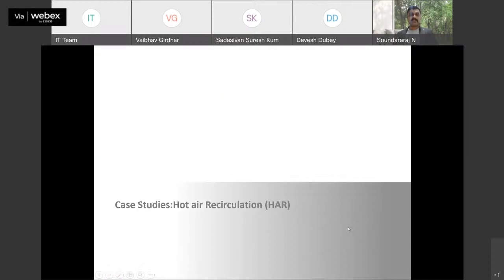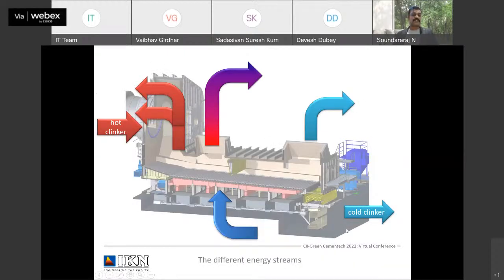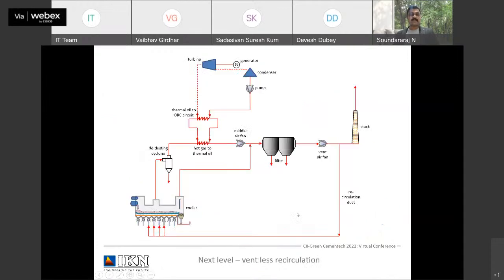The further case studies are on the hot air recirculation system. WHR is an emerging trend in this industry. Everybody wants better recuperation and at the same time better WHR generation. How will you achieve this when the customer decides to replace the inefficient cooler to improve recuperation, and how do you maintain both recuperation and WHR? With the ventless recirculation system, you can have your cake and eat it too. With this method, the additional heat available at the stack, between 100 and 120 degrees, can be recirculated back to the cooling fans to increase the mid-air temperature.